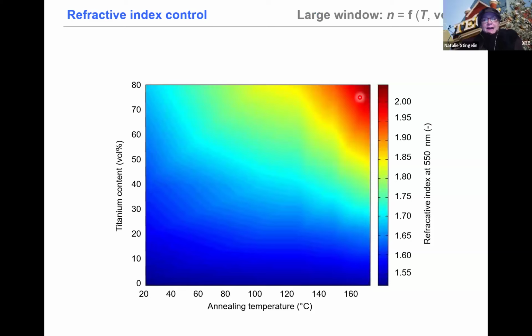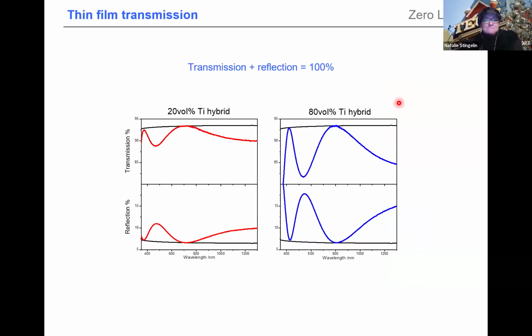So we really have a highly tunable system where we go from a refractive index of 1.55 here in blue, the neat polyvinyl alcohol, to close to a refractive index of 2.01. Usually it's like 2 maximum.